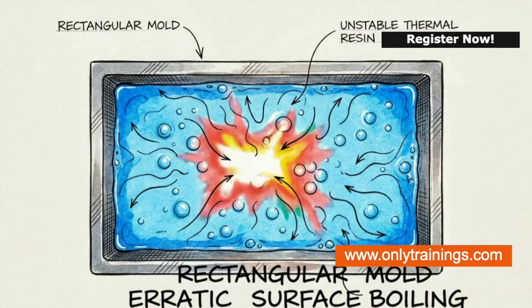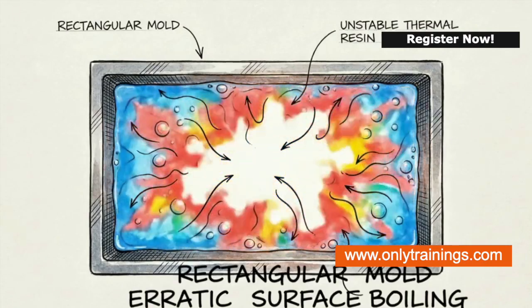Without the original styrene architecture, the new reactive monomer generates highly unpredictable peak exotherms compared to the historical baseline of the resin. This thermal volatility causes gel times to drift wildly from batch to batch. The secondary consequence is severe, drastically altered shrinkage behavior as the part cures.